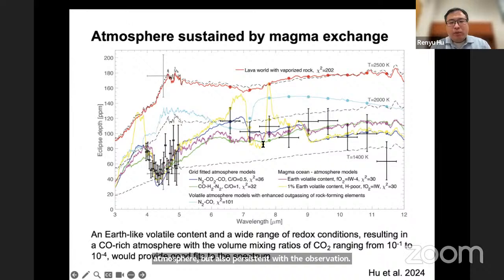Alternatively, in a broad sweep of parameter space, we have simulated over 3,000 self-consistent atmosphere models covering C, H, O, and S abundances, and we form a grid to see which combination of gases provides a fit to the data. The best-fit models also center around CO2-rich atmospheres or CO-dominated atmospheres. In this broad sweep of parameter space, we also found that the presence of water, sulfur dioxide, and sometimes phosphine can improve the fit to the spectral modulation seen between 4 and 5 micron in some cases.